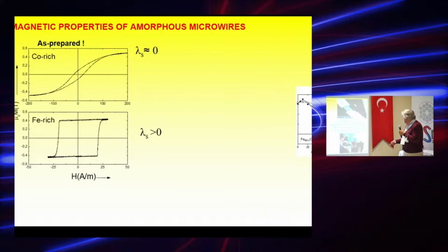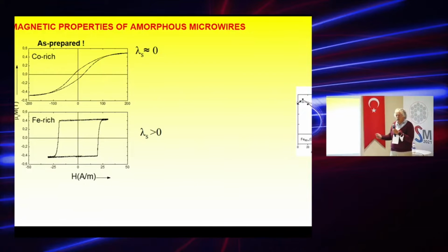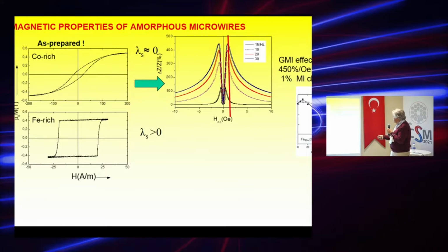Since the alloy can have different compositions, we can have different magnetostriction constants. This was already mentioned by Larissa. For example, a composition with nearly zero magnetostriction can present an almost linear hysteresis loop with very low coercivity, while the iron-rich materials, which in fact are much less expensive and much cheaper, present this square hysteresis loop. This picture demonstrates that if you change the relationship between iron and cobalt, you can tune the magnetostriction coefficient of our material. These cobalt-rich materials can present a quite large giant magnetic impedance effect, which is suitable for sensor applications.